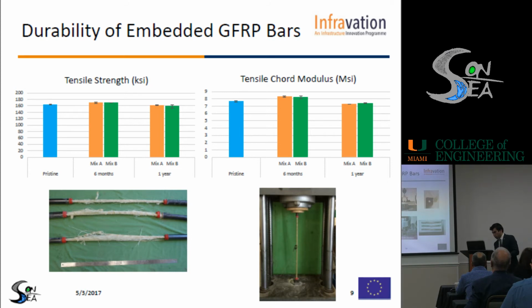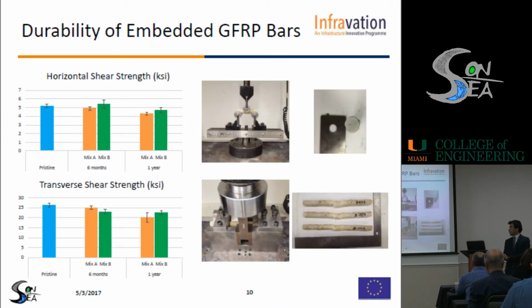So we go to the other test, the horizontal shear test. That test, again, I showed it. It's a really good quality control test. And the test setup I showed you before. So that's the type of failure that you can get. So this is pristine bars, and then this is 6 months. So for mix B, which is a seawater concrete, we had higher results after 6 months. And then when you go to 1 year, although the shear strength goes down, still mix B, which is a seawater concrete, has higher results for the horizontal shear strength.